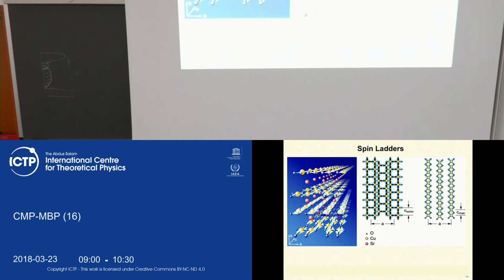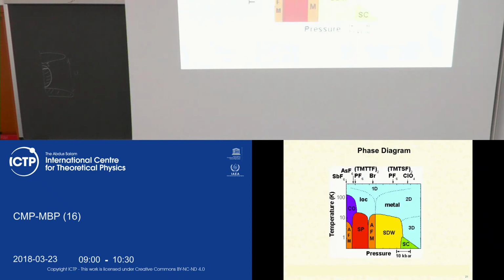And one can actually think about dimensional crossover. So suppose that there is some quasi one-dimensional chain of ladders, and you start to couple it weakly and produce a two-dimensional object, or you couple it in both directions and produce a three-dimensional object. And this is another way to construct theory basing on exact solution for one-dimensional. So the good thing about one-dimensional systems is that in several cases exact solution is possible, and therefore, constructing exact solution for chains and using hopping from chain to chain as a perturbation, one can actually increase dimensionality and construct perturbative solution of a high-dimensional system.